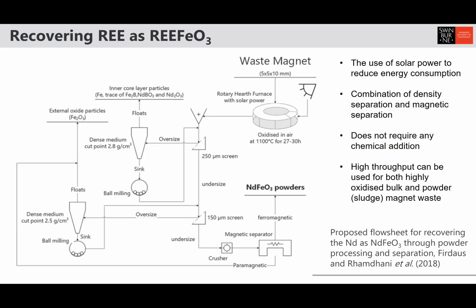So first, we use solar energy to reduce the energy consumption because we found that the process takes 24 hours at least. Right? And so the idea is we use rotary hearth furnace with concentrated solar energy to oxidize the magnet. And then we use a series of physical processing that combine density separation and magnetic separation to separate NdFeO3 from this magnet. Yeah. So in here we don't need to have other chemicals and it's just a concept that we develop and we're currently developing this and fine tuning the process.